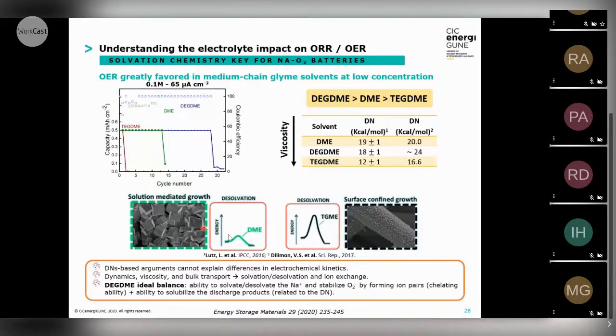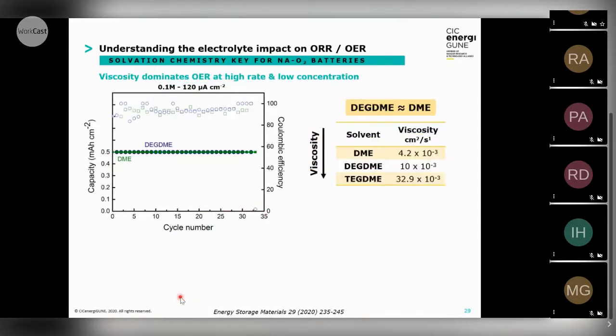So here we know that the desolvation energy of the DME, because it's less bonded, is going to be lower, and in the case of the tetraglyme, it is going to be higher. And in this case, the diglyme was a better solvent because it was a balance, the ability to solvate and desolvate the sodium, and also stabilize the sodium superoxide in solution. And also here, related to the donor number, you can know the ability to solubilize that discharge product. When we go to higher rate, the performance of these solvents is really similar.